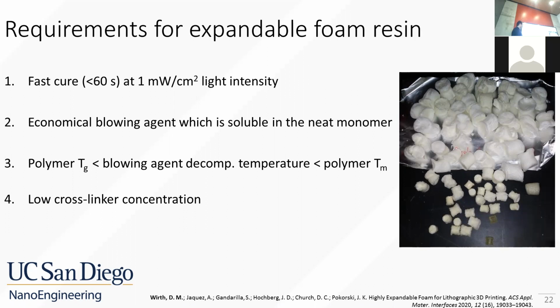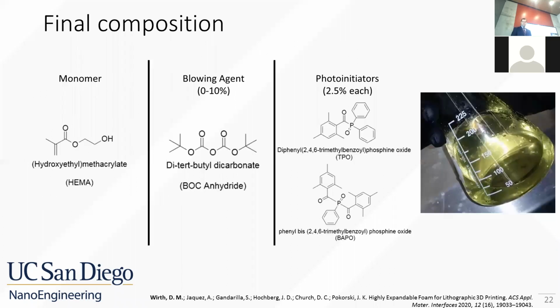If it decomposes too early, the polymer is not going to be compliant enough to expand. And if it decomposes too late, you're going to lose all that structural information that was imparted during printing. Finally, we want a resin with a low cross-linker concentration. Cross-links increase the glass transition temperature and reduce the free volume of the polymer, thus reducing expansion.